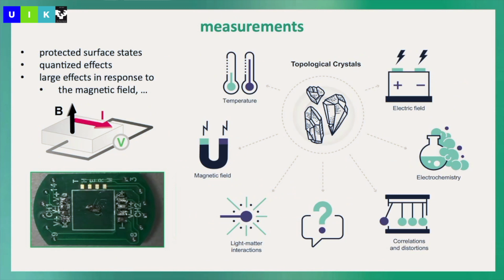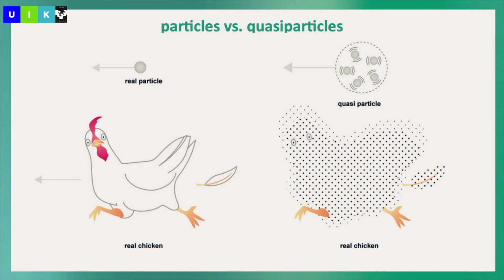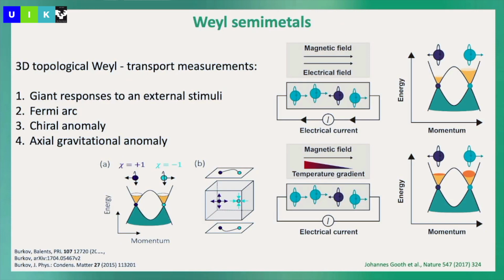Despite measuring our crystals, we have many ways also to have knobs to tune properties in these materials. Not only the magnetic field, we can use light-matter interaction and so on. You can change the temperature, which is important, and you maybe can even change the position of the magnetic field relative to the current, because for the chiral anomaly the prediction was to do this E dot B. Anyway, we cannot now investigate particle and antiparticle, but this is a nice thing also of physics. You don't measure the particle, you measure it as a quasiparticle, which is sometimes also dangerous because then people can start to discuss, do you really measure the particle or what are you measuring? So the quasiparticles. Anyway, Weyl semimetals, because of this Berry phase with different signs, are very interesting, and there's a list of interesting properties you can measure, so this is a starting point.